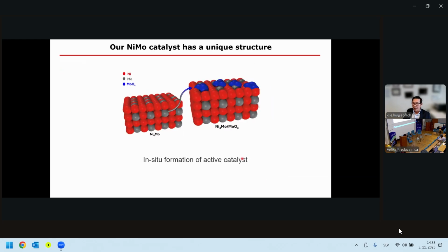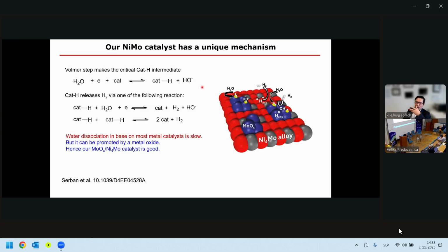We found, actually, typically when you make a nickel molybdenum catalyst, this is why you have nickel 4 molybdenum, but in our case under operation, due to our procedure, we end up with a catalyst with a base of nickel 4 molybdenum, but on our surface we actually have excess molybdenum oxide. And this is really interesting because based on electrochemistry theory, for water splitting, hydrogen evolution in alkaline conditions, you take water and you make a surface hydride, a surface adsorbed hydrogen species.